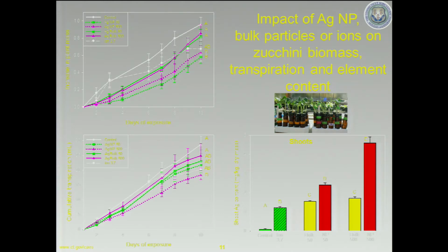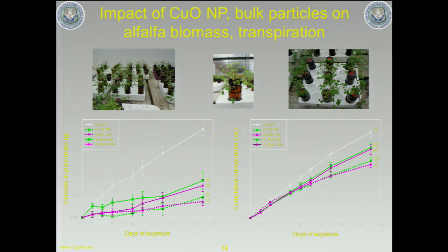You compare the white line with all these different concentrations. We tried different concentrations, and this is the control, which does not have any nanoparticles. Compared to the control, you look at these graphs and you get an idea. Anything that is below the graph is toxic, but it also has to be statistically significant. If it falls under the statistically significant area, then you cannot definitely say it is toxic. This was silver, I think. When we did it with copper oxide, it turned out to be extremely toxic.